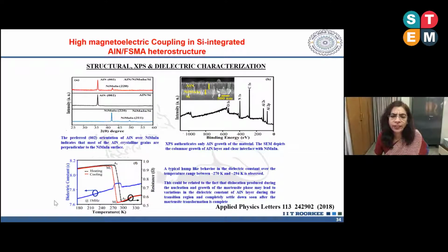Okay, so this is the aluminum nitride structure, and here again we got the dielectric constant versus temperature plotted. Similar to the PZT case, we got a hump, which shows that the two layers are coupled.